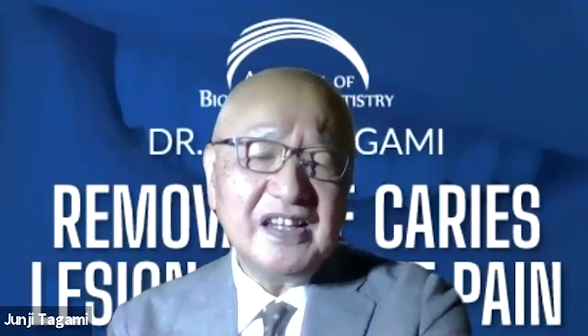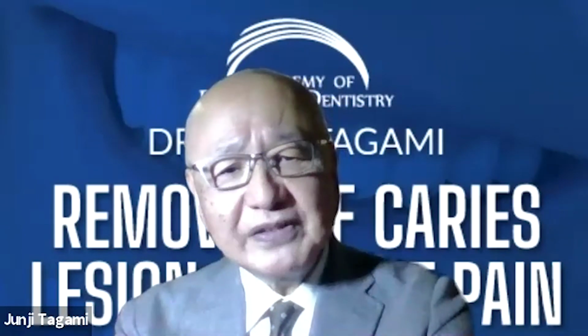To avoid that kind of phenomenon, sometimes the enamel margin is etched with phosphoric acid even when we use the two-step self-etching material. But in our recent study, the DEJ is very heavily damaged by the phosphoric acid. And sometimes the DEJ is broken and separated, and a gap is observed in the cavity after the polymerization of the composite, especially when we use phosphoric acid etching on the DEJ. So that's why the application of phosphoric acid to the DEJ is strictly avoided.